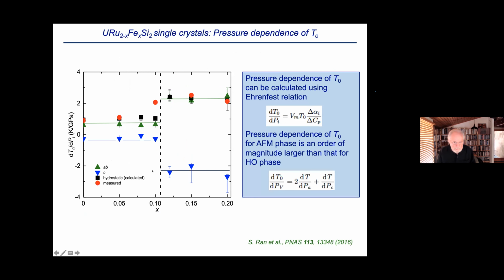And if you take these data and calculate the pressure dependence of the hidden order transition using the Ehrenfest relation, then you get these black points right here. And then those can be compared with the actual measurements made in a piston cylinder cell, just detecting the hidden order. And those are the red points right here. So you can clearly see this line that delineates these two phases from one another, makes this phase boundary.